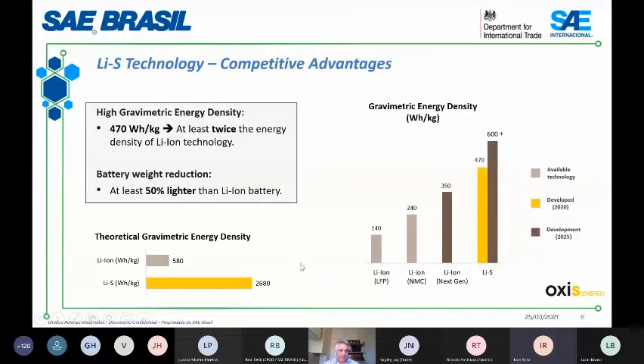And I think it's important to have a look at the theoretical gravimetric energy between lithium ion and lithium sulfur. It is about 5 times. 580 watt-hours per kilo against 2680 or something like this. So this is important to understand the possible future development and improvement of our technology, even higher than 600 watt-hours per kilo. And then together with the high gravimetric energy density concept, there is the battery weight reduction. Our batteries are at least 50% lighter than lithium-ion batteries, and in the case of LFP, it will be much more than just a 50% reduction.